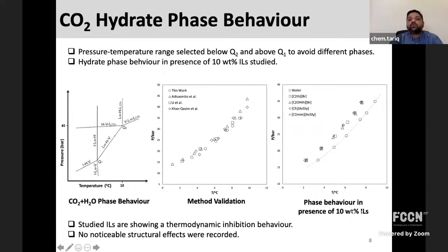So this is the CO2 hydrate phase behavior in presence of 10 weight%. We have chosen 10 weight% because it is generally the reference concentration where all the additives were screened. And we are always in between the Q1, Q2 quadruple points, because CO2 can form different phases and hydrate in different ways. But we restricted ourselves to this region where you have always liquid water, hydrate, and vapor. And then first of all, we validated our method and our apparatus, and we found that it is in good agreement with the literature.